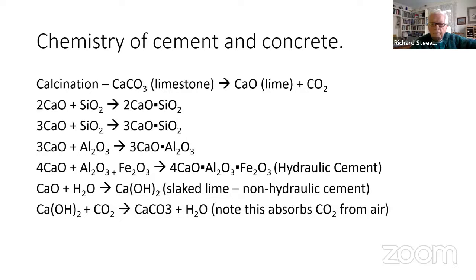Another thing that I would assume everybody's heard about is this slaked lime. I never really knew what it was before, but it's just calcium hydroxide. It's calcium, or the lime, and you add water to it, and it's often used as a cheap mortar. And then you also see here that if you add CO2 to the calcium hydroxide, that slaked lime, it will actually absorb CO2, which is the reaction that Richard was just alluding to. So during the hardening, or when you add water to Portland cement, after a time, it will actually absorb some CO2 from the air.